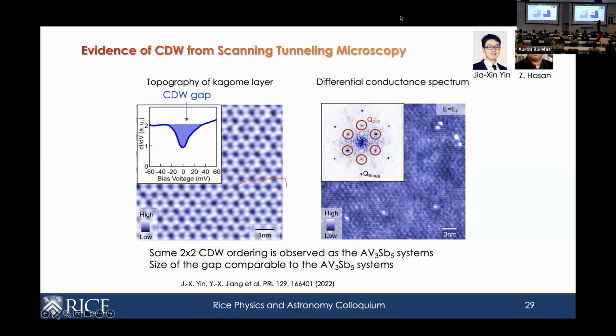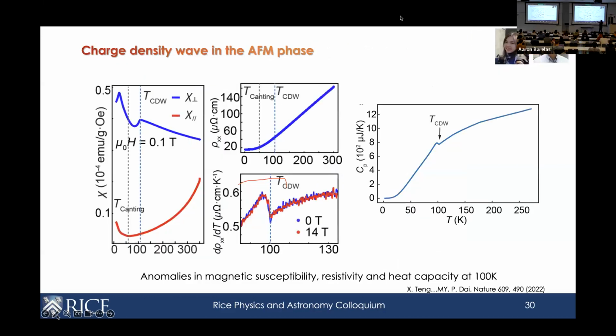And you can see a gap developing in the density of states. And also, if you have a phase transition, you better have some sort of signature in your heat capacity. So here, this is a heat capacity measurement showing a phase transition around 100 Kelvin, which confirms the CDW order. There are also signatures in the first derivative of the resistivity, shown here, and also magnetic susceptibility, and so forth. So this really confirmed from many different techniques that this is real CDW order.